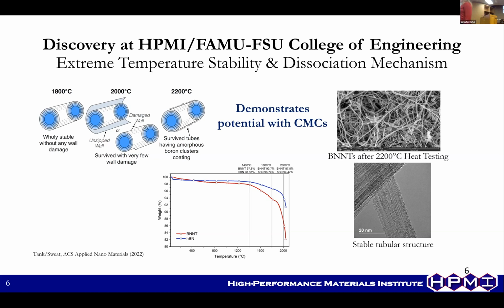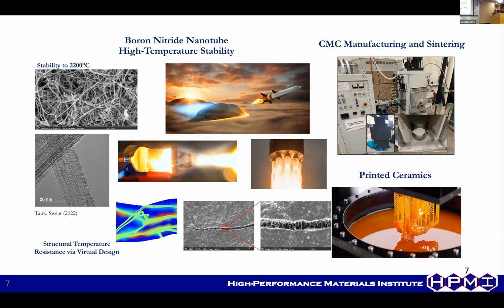So upon very thorough investigation, and this is published work if you're interested, the decomposition was with unzipped walls, damaged walls that initiated at defect sites, initially at the high temperatures, and would unzip a wall. So these BNNTs are anywhere between 2 to 10 walls. So even though you have retained tubular structure, some of this amorphous material you can see at the surface could be unzipped walls that have happened on the surface. So we've demonstrated why they're a good candidate for some of these properties.